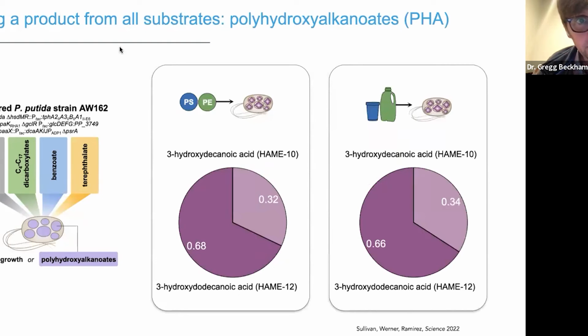And this is making a product from all the substrates now. So all of the products go to both growth and polyhydroxyalkanoates. And you can see, as you would expect, when grown on these mixed substrates, the organism is able to produce polyhydroxyalkanoates, which is really, really exciting. And this is, I should say, the natural carbon storage product of this organism.